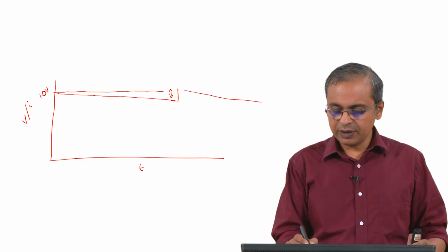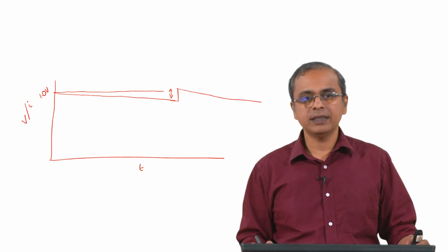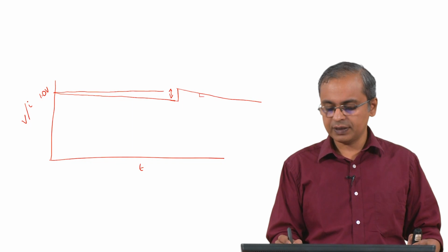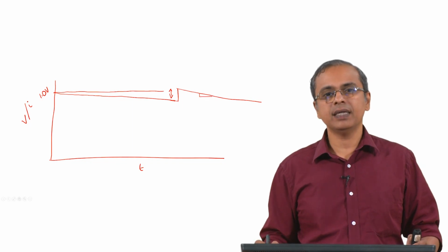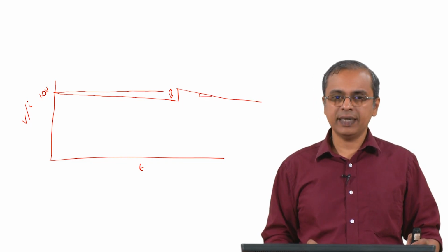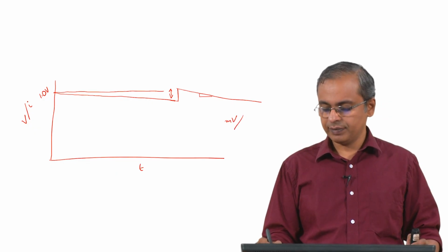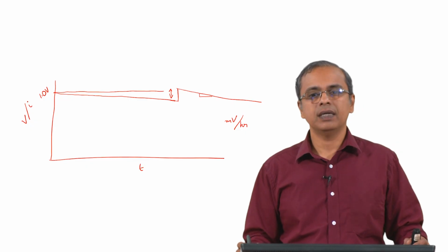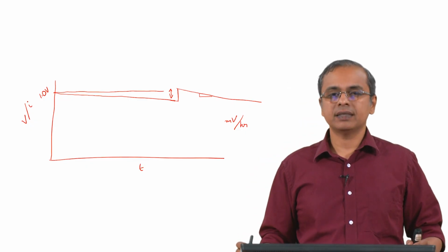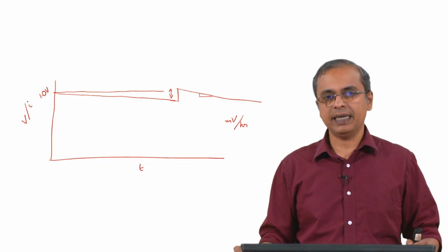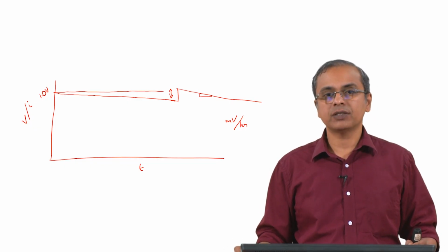A lot of diagnosis is done using this. First of all, people look at degradation rates. They look at the slope of this line here, and that represents a degradation rate. We talk of it in terms of millivolts per hour. Millivolts per hour degradation rate is something that people try to actively keep track of for many electrochemical devices, and so they will have a target.